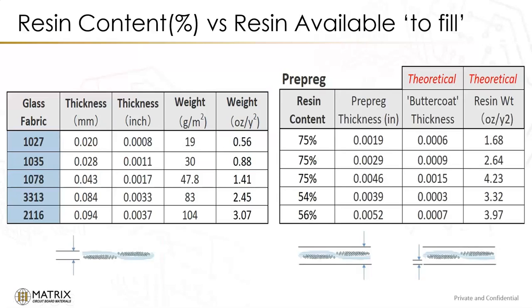In the column next to that is more of a reference value than anything else. I'm not considering the density of the resins, I'm just doing a percentage of it. If I know the glass weight and I know the percentage of resin to the glass, I've come up with this little factor here that I use. You can see that not only does the 1078, 75% have the most resin on the surface, but by volume, if we look at it that way as a factor, it's got the most by volume as well. And you can see the 1027 has the least amount.